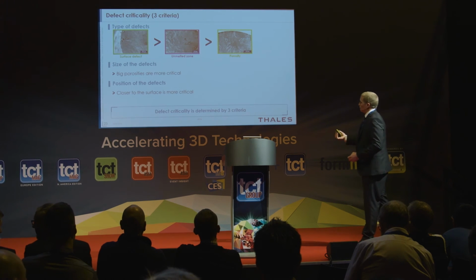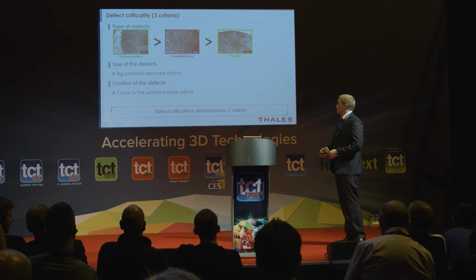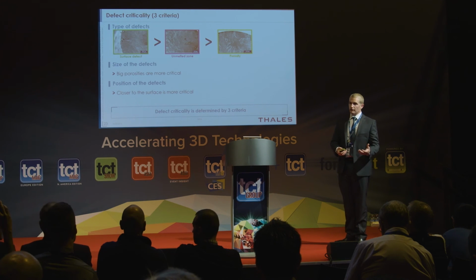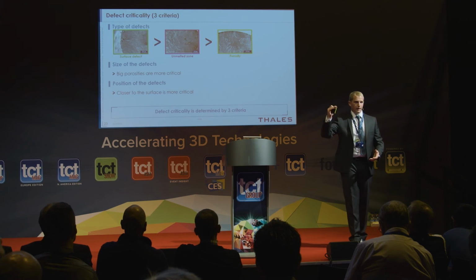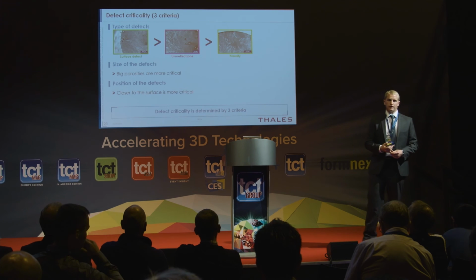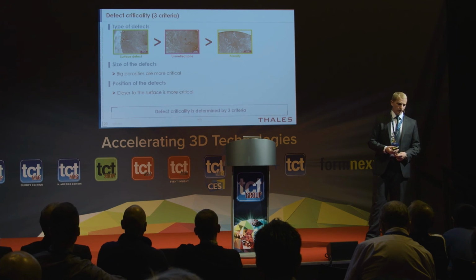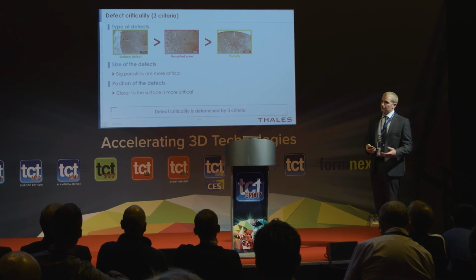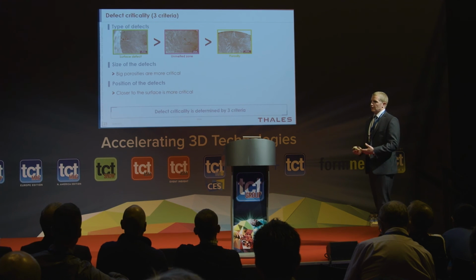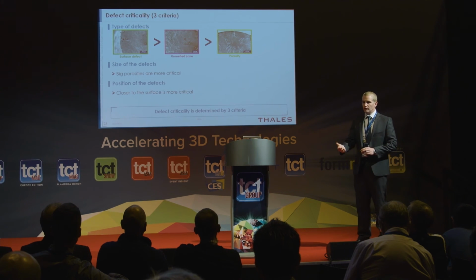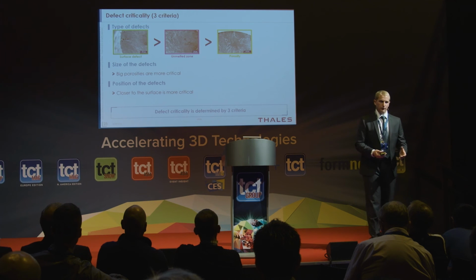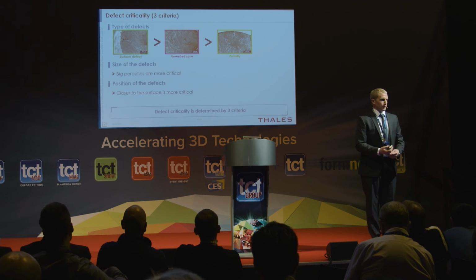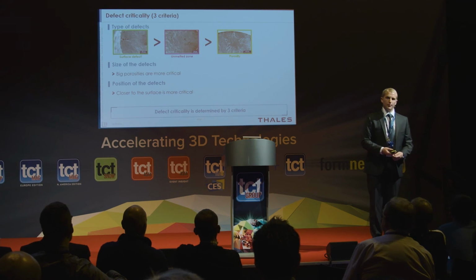Turns out that from what we found, big porosities are more critical, causing an earlier failure, even though they're right up on the far right hand side of the chart we saw earlier on. But at the same time, if they're close to the surface, they're also more critical. So when you're doing your analysis of your parts in the qualification stage, these are some of the things we found that we need to look for when we complete our scanning.